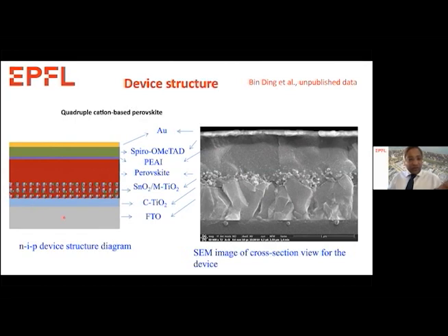So here, the way I have discussed, we have a conducting glass, FTO, followed by a compact layer of TiO2. On top, we have deposited a mesoporous TiO2 layer. And remember, here we have a thin layer of tin oxide on top of the TiO2. Why we are using two metal oxide layers, you will see towards the end of my presentation, around slide 47, where we are using two metal oxides to improve the stability.